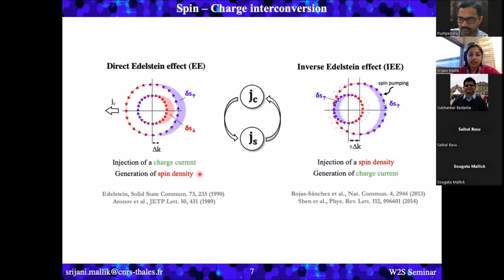So this means the systems having this kind of Rashba contours are basically very nice for such spin charge interconversion. And one very important figure of merit I would like to mention here is the figure of merit for spin to charge conversion. That's the ratio between the charge current and the spin current. And this is proportional to two things. One is the Rashba coefficient, and another is the momentum relaxation time, tau. So lambda is proportional to both alpha and tau.